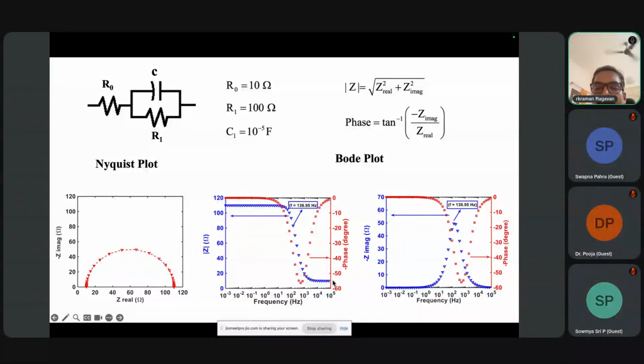Okay. And if you look at the phase angle, remember the phase angle in case of impedance: in case of a resistor, when we apply the voltage perturbation, the current was in sync with the voltage. There was no phase difference. Whereas in case of a capacitor, there was a phase difference of 90. So at a very high frequency, what you see is only the resistor, because the capacitor acts like a short. At again very low frequency, you see only these two resistors playing, because the capacitor is exhibiting a very high impedance in this case. So current was going through this arm. Therefore, at very low and very high frequency, you have a phase angle of 0, but at mid frequencies, it goes up to close to 90. Okay, this is a Bode plot that tells you how many RC processes or time constants are present in your system. Each time constant is equivalent to the charge transfer reaction that we have in this case.